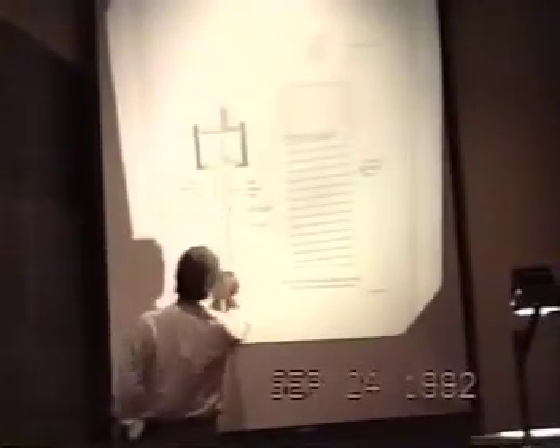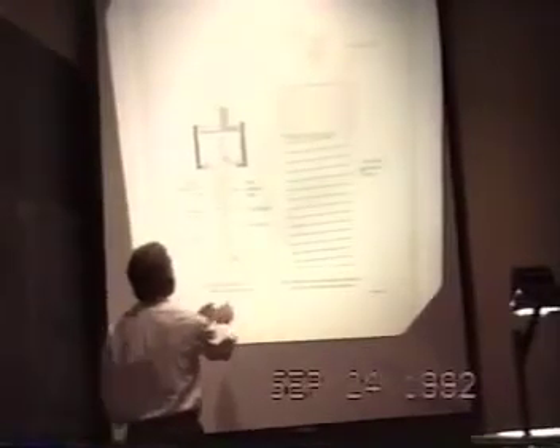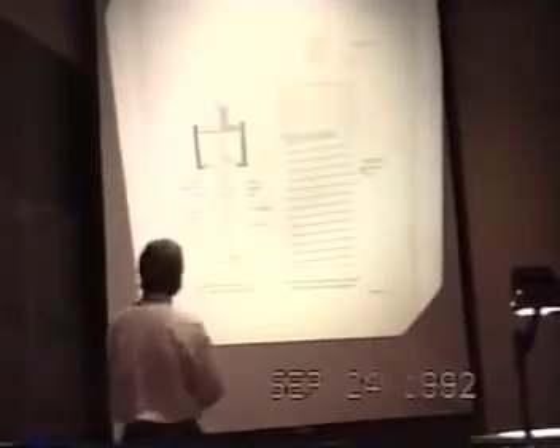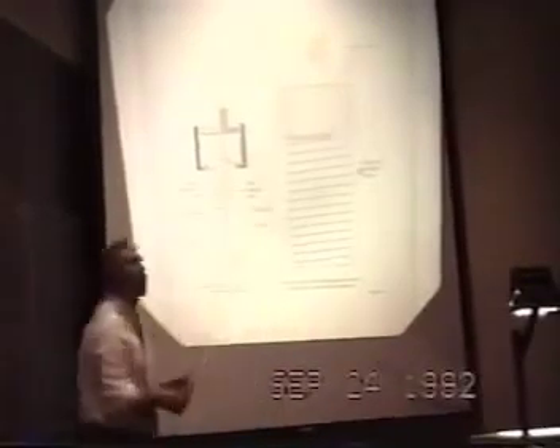Experiments that were by and large performed in an electrochemical environment that looked like this. A 3mm palladium cathode, either 3 or 5 centimeters long, a helically wound platinum anode, 1 molar LiOD electrolyte, to which additions were made of the elements aluminium, silicon, and in some experiments boron. This is mounted inside a pressure vessel so that we can apply a small overpressure of deuterium, and the pressure line is connected to a pressure transducer, which is sitting above the level of the electrochemical experiment.